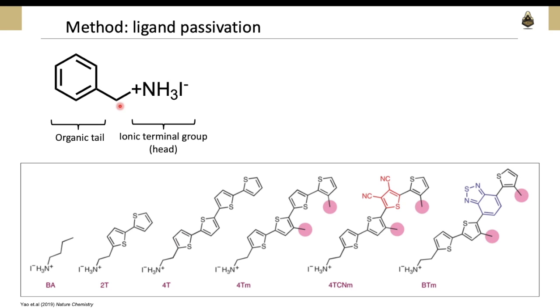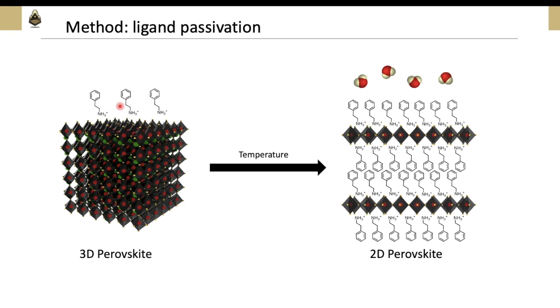Here is an example of a study done by Dr. Gao in our group that demonstrates the synthesis of this type of ligands. Upon heating, these ligands diffuse into the perovskite structure, and the ligand heads fill the organic cation vacancies, while the bulky organic tail line up in a uniform direction to accommodate limited space. In this way, we convert the surface of the three-dimensional perovskite layer into two-dimensional perovskites.